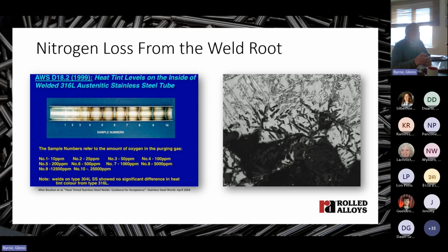Now, over-purging of the pipe bore causes nitrogen to diffuse out of the molten weld bead and into the pure argon backing gas. Now, nitrogen partitions to austenite preferentially in these alloys, so nitrogen loss lowers the corrosion resistance of austenite in the weld microstructure, and this causes the austenite phase to pit out during corrosion testing. This is a section through a corrosion test coupon that's pitted, and we can see here that austenite is preferentially pitting out, and that's an indication that we've lost nitrogen during welding. And you'll recall that the multiplication factor is a factor of 16 for nitrogen in the PREN equation, so it's a very important element for corrosion resistance.